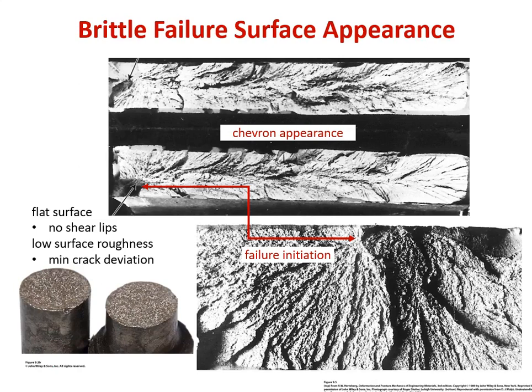If you look in the lower left-hand corner, there's a round tensile bar, very analogous to the one that we saw with the round ductile failure with shear lips. This one looks flat across. It's got a little bit of a sugar crystally appearance. There's a very small amount of roughness and topography. But most important, there are no shear lips. Because there was no ductile failure, there was very little deviation of the crack going straight across. It had very little reason to change direction. So it almost looks like a perpendicular fracture surface.